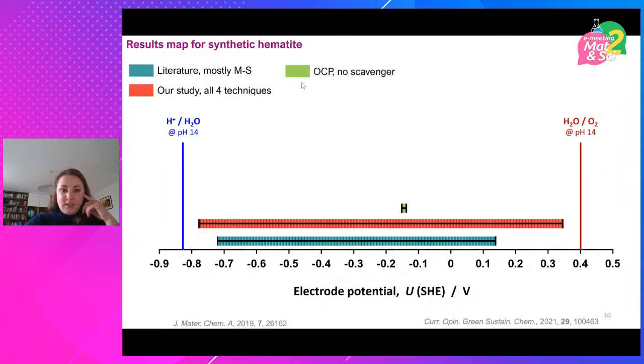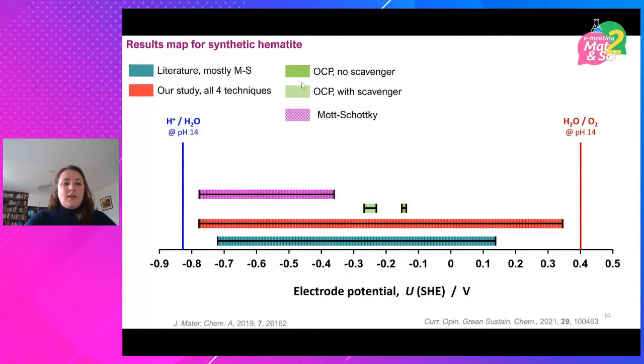So in terms of the 4 techniques, if we measured the open circuit potential without any scavengers, so let's say 1 molar sodium hydroxide, we got a really neat range of values, almost believable. When we then put in a scavenger, so I think it was hydrogen peroxide, we got a slightly higher dispersion, but the values were a fair bit different, so considerably more negative. And we thought, oh, okay, well, maybe with the scavenger, that's the real value. Maybe it prevents Fermi level pinning or something like that. And then we did Mott-Schottky, and the values were way to the negative side, which I would say was more consistent with the bulk of the literature. But those values didn't overlap at all with the open circuit potentials.